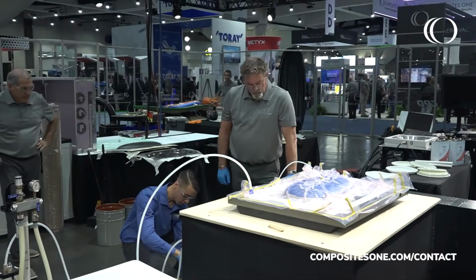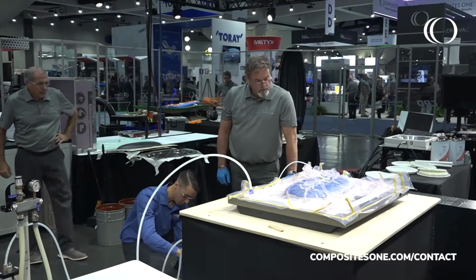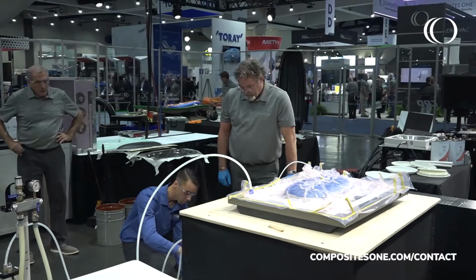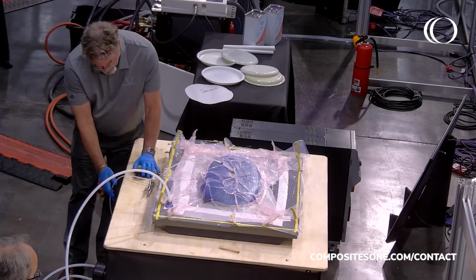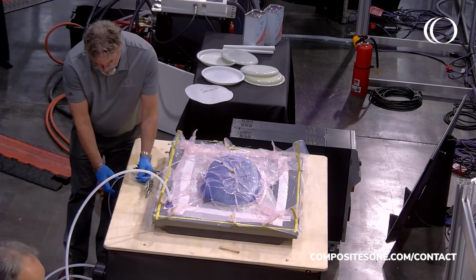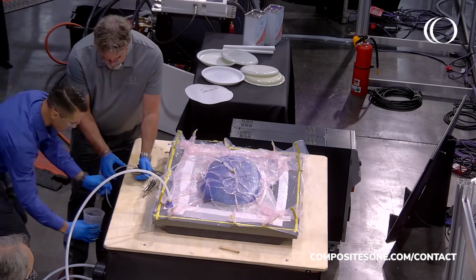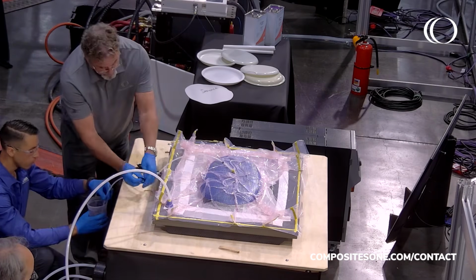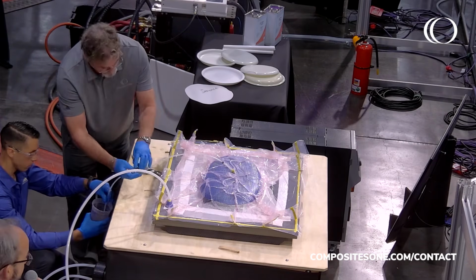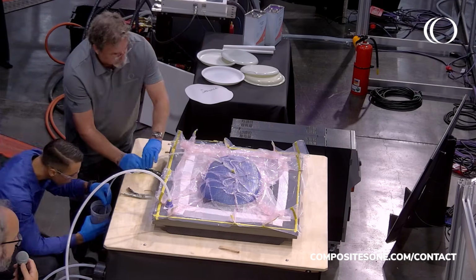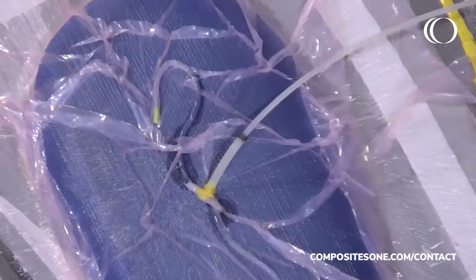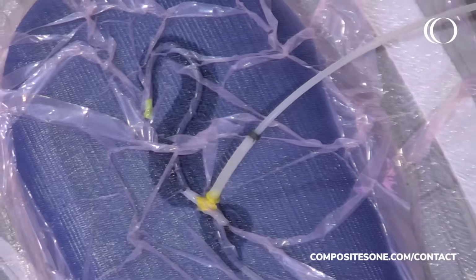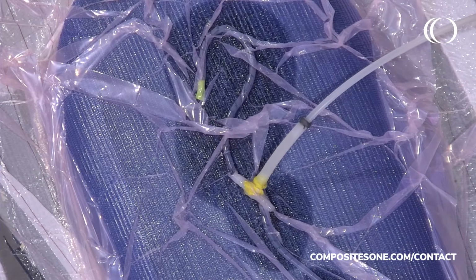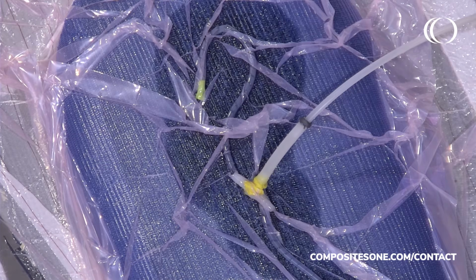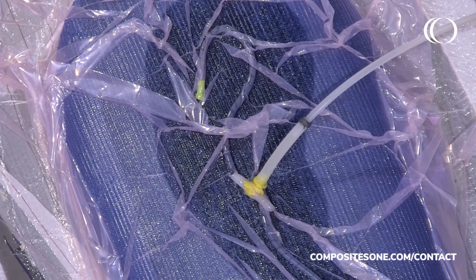So Barry has actually increased the mold surface temperature to 110 degrees Fahrenheit. Our resin is mixed, and we're going to open the feed line, and you'll be able to see the resin flow through the InfuPly. And then there's a slight lag between where you see the resin flow in the InfuPly and where the resin is on the mold surface. And that's why we have a resin break around the edge of the part.